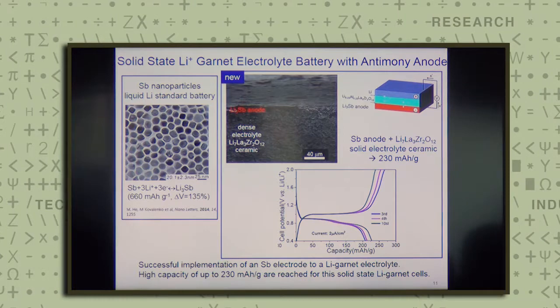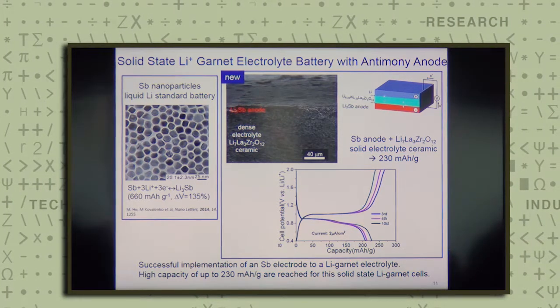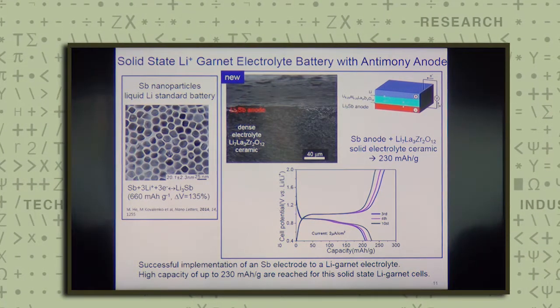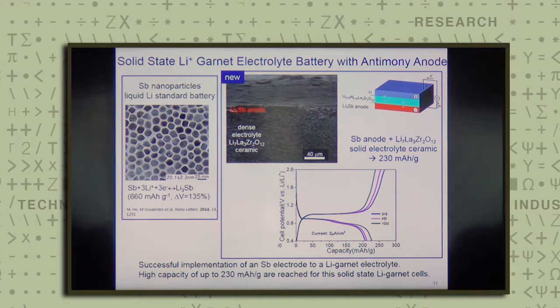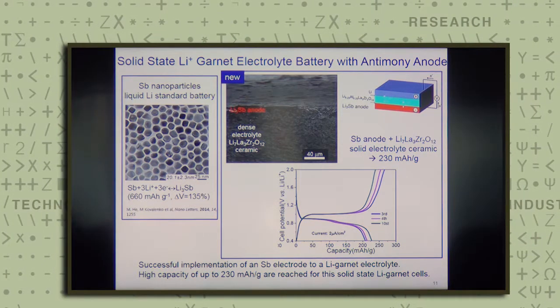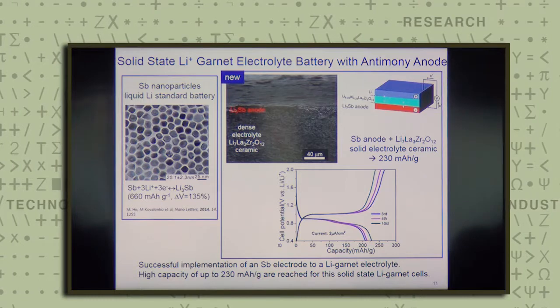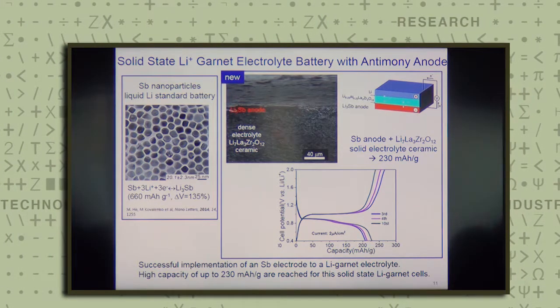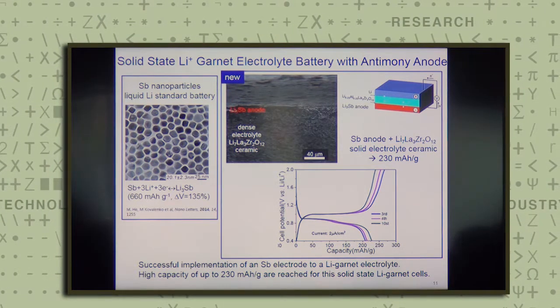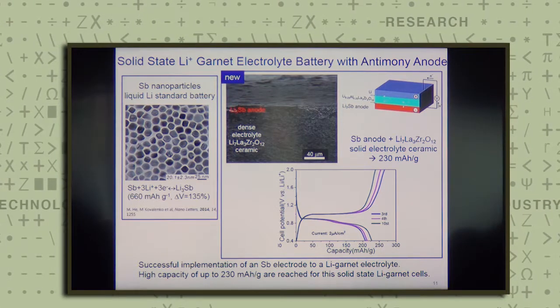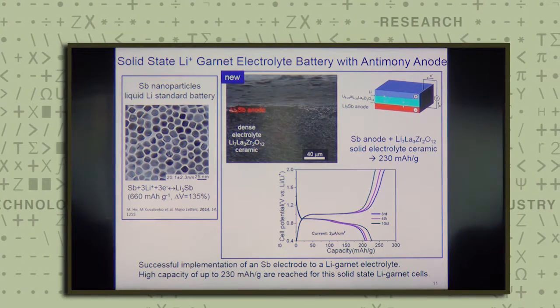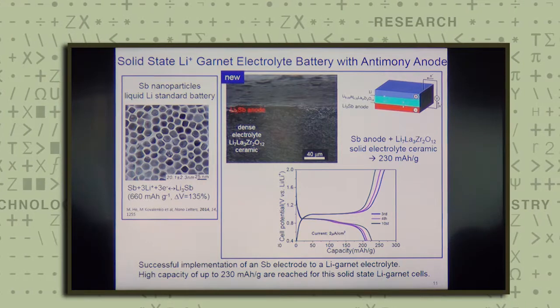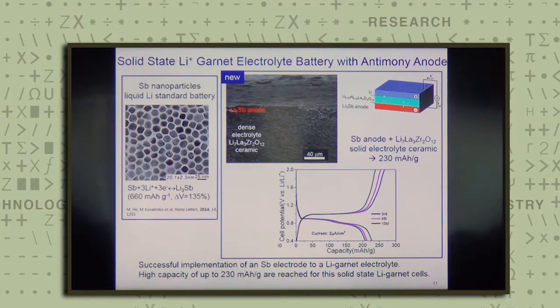And so actually with that lesson learned, we can also start to compose solid-state battery cells with such an electrolyte, and on top of it take a softer material like antimony and compose antimony nanocrystals on top. And here we come actually to relatively high lithium garnet performances of the cells of about 230 milliamp hour per gram, which gives you a perspective actually on using these solid-state and safe batteries as an alternative.